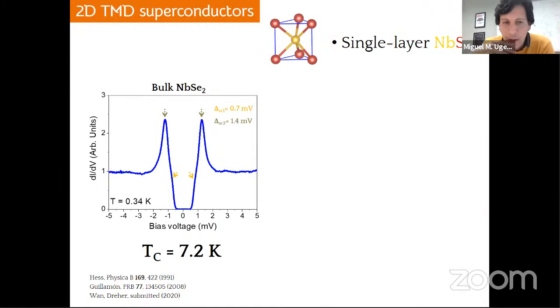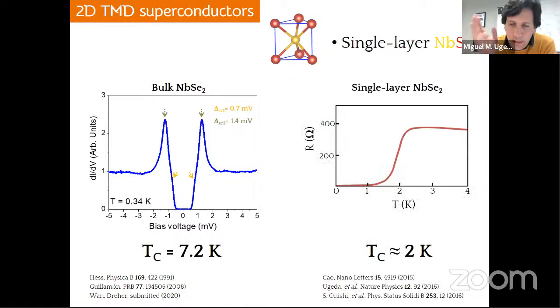In terms of superconductivity, this material in bulk is a superconductor. It has a critical temperature of 7 Kelvin, and it's a multiband superconductor. So you can see in the dI/dV spectra that there are two different gaps. One of them is 0.7 millielectron volts, and the other one is 1.4 millielectron volts. When you go to the single-layer limit, the system is still superconducting, but with a critical temperature of around 2 Kelvin.